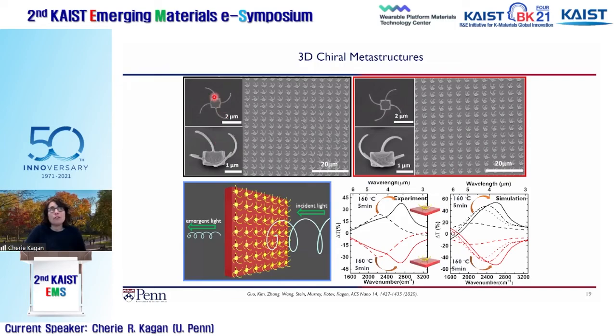So what we do is pattern these structures that I think of as looking like pinwheels in two dimensions, as you see in the examples here on the left and here on the right. And then we could do this over very large areas. And so you're seeing examples here of some of the large area structures for the two different enantiomers that we can make by these fabrication processes. And if we further anneal the structures, we can get them to bend even further. And you can see these three-dimensional structures that are bound to the surface here in these electron micrographs.